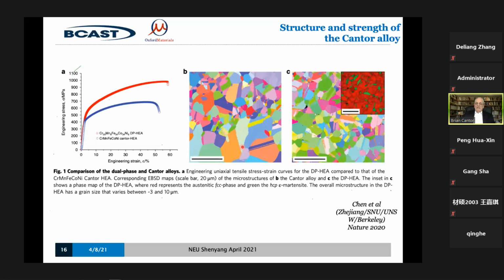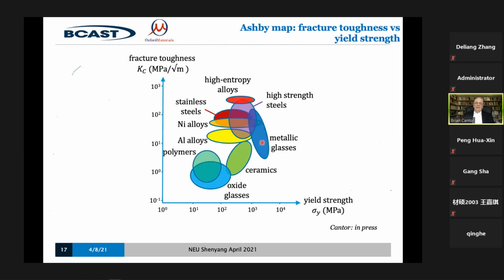And in fact, if we plot an Ashby map, and of course you can make it stronger still by doing the same sorts of things as you do to high-strength steels or high-strength aluminium alloys. You can add other components, and you can play with the composition. So this is why people are interested in this material, the Cantor alloys, because if you plot it on an Ashby map of fracture toughness against yield strength, down at the bottom here, you can see polymers and glasses and ceramics. They're not very tough because they fracture easily.